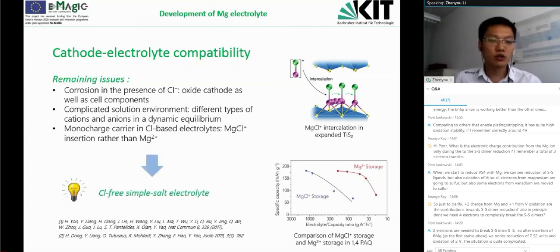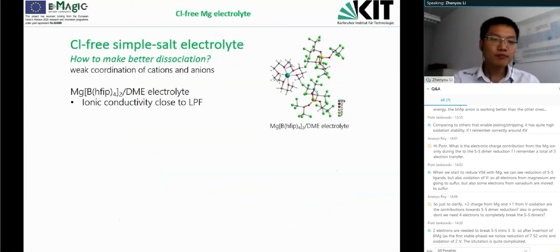So there's an urgent need to develop a chlorine-free simple salt electrolyte. And we also work in this direction and develop the electrolyte of such kind. And here is the structure of this electrolyte. So basically, we have a large anion, which contains a boron center and this fluorinated alcohol ligand, and this makes a weak coordination between the anion and the cations, and also this means we have better dissociation and higher ionic conductivity in the electrolyte solution.